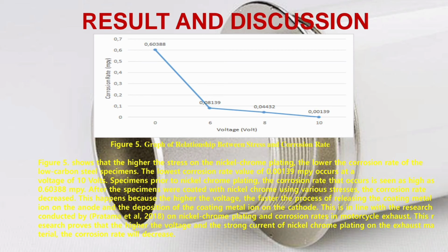This happened because the higher the voltage, the faster the process of releasing the coating metal ion on the anode and the deposition of the coating metal ion on the cathode. This is in line with the research conducted by Pratama et al. 2018 on nickel chrome plating and corrosion rate in motorcycle exhaust. This research proved that the higher the voltage and the strong current of nickel chrome plating on the exhaust material, the corrosion rate will decrease.